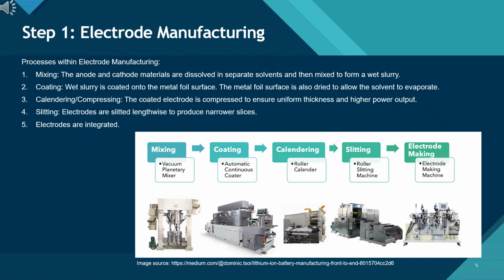After coating, the foils pass through the roller calender. This machine compresses the electrodes to the target thickness and porosity, improving energy density and uniformity. Then we move to the slitting machine, which cuts the wide electrode rolls into narrow strips that match the size of the cells. Clean edges are important here to prevent short circuits. Finally, the electrode making machine integrates and prepares the finished electrodes for the next step, cell assembly. Each of these machines must run precisely. When they do, we get stable, high-quality electrodes, which are the backbone of a reliable battery.